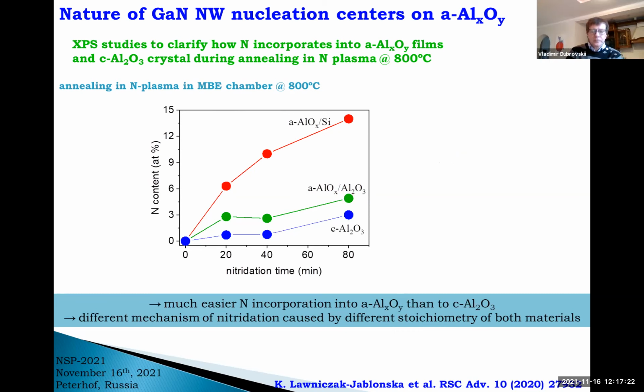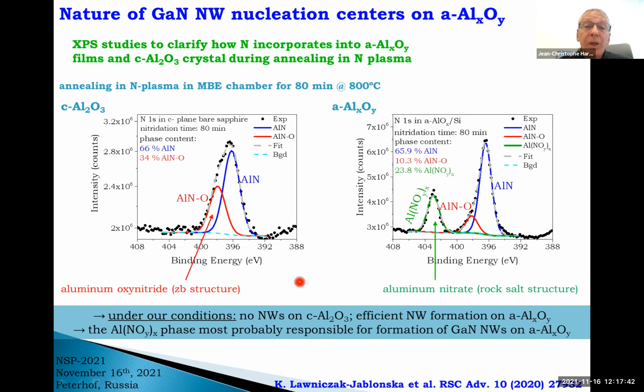Jean-Christophe, yes, please. Good morning. Thank you very much for this very interesting talk. I also have a question on this aluminum oxynitride formation. In your XPS study, the sample was just exposed to nitrogen alone. Is that right? Yes, what we did, the sample was exposed inside the MBE chamber to nitrogen plasma for a given time at temperatures which more or less corresponded to the incubation conditions of nanowires. So there was no gallium flux. No gallium flux, in that sense, yes.